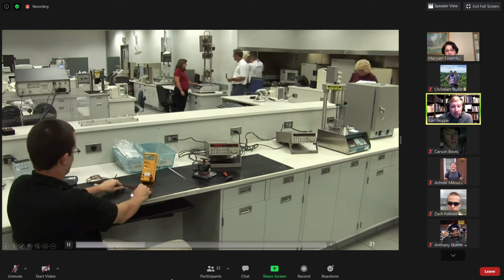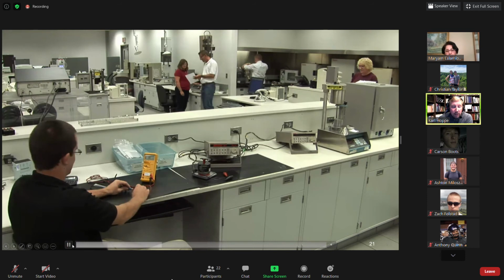He's going to be doing a volume resistivity test, where you're actually looking at how much electrical resistance goes through this bar. You can see the ends of the bar kind of abraded, and there's a silver paint applied. So you're not testing the conductivity across the surface, but actually through the volume of the material. Similar test, but then looking specifically at the surface, is this guarded ring test, which is measuring surface resistivity.